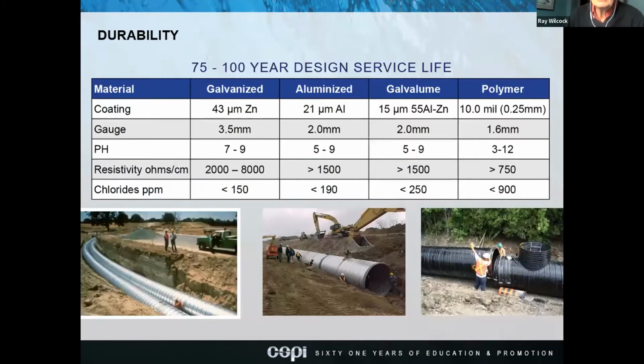So here are the 4 coatings, and this is how you would get a 75 to 100 year design service life from these 4 materials, whether it be galvanized, aluminized, galvalume, or polymer, based upon these types of chemistries that you're dealing with. So for instance, you have the coating across the top, you have 43 microns of zinc for galvanized, and then going across the page, you will see the different coatings for the different materials.